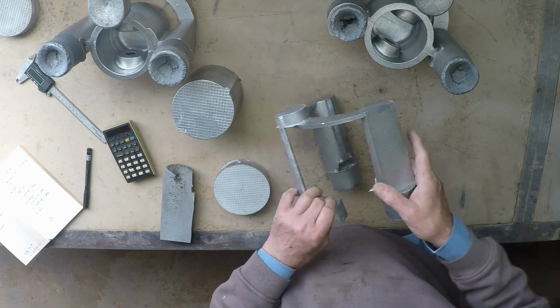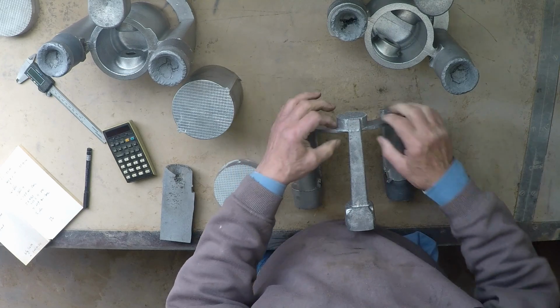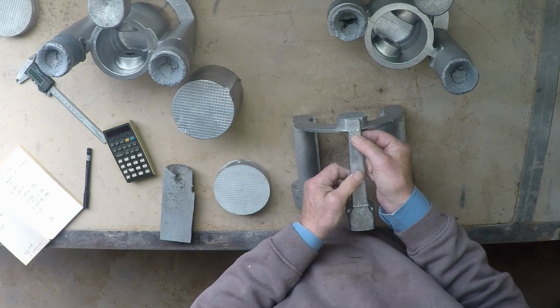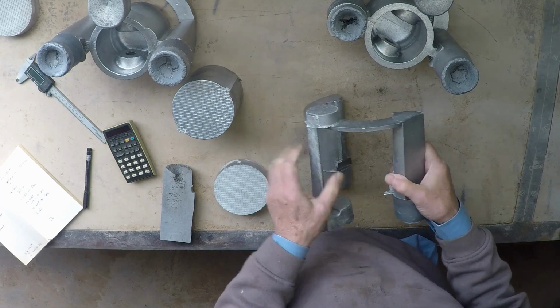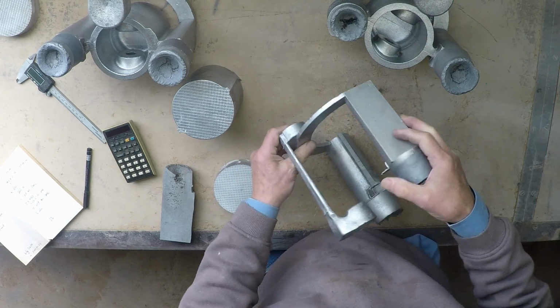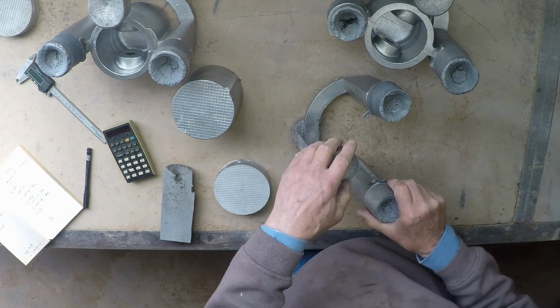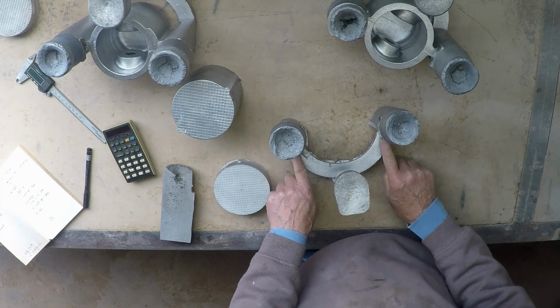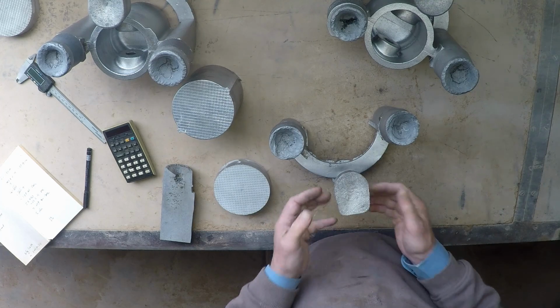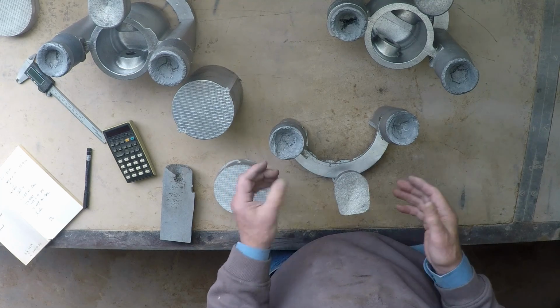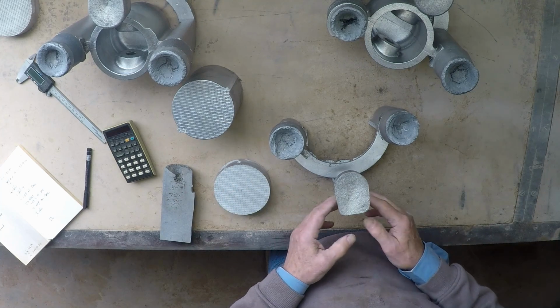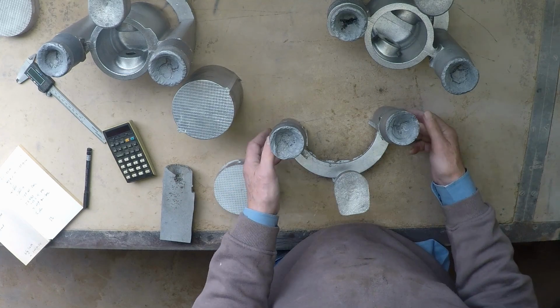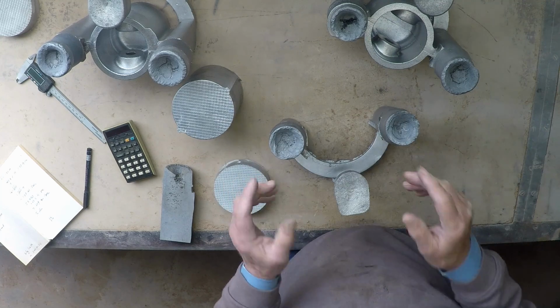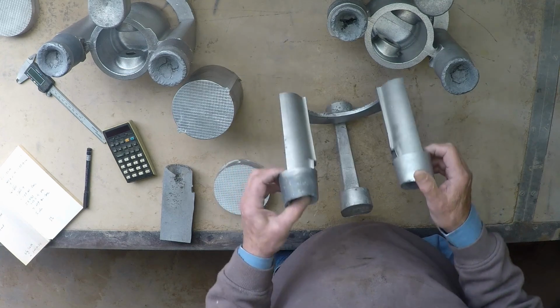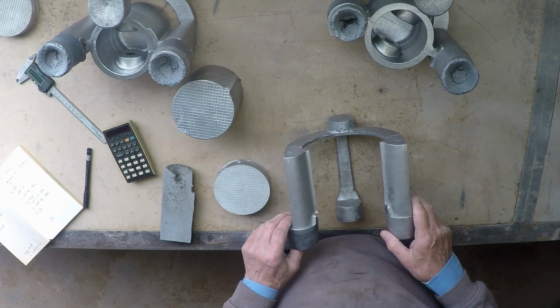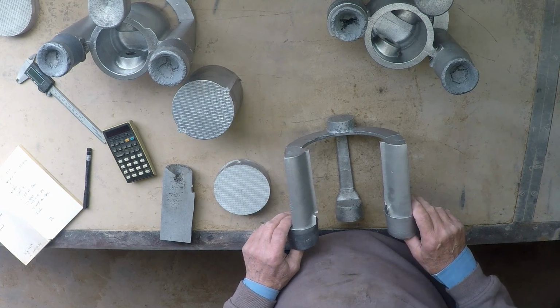And we've deliberately made this runner bar in total 4 times the area at the base here of the sprue. So the metal velocity here should only be 0.5 meter a second. Then it goes into the 2 feeders. Any air that does get pulled down, and when you first start a pour, you're always going to get a little bit of air pulled down, will go into the feeders and come straight up the feeders. They won't go into the casting, and they won't damage the casting. So in that way, we hope that this gating system is giving us the best possible casting.